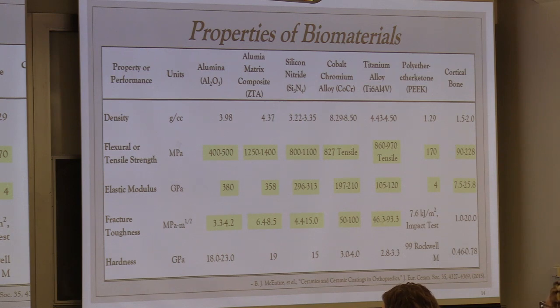But note that alumina has a fracture toughness which is essentially half or even a quarter of that of either ZTA or the silicon nitride material. And we're going to explore a little bit why that is the case. But these materials, the ZTAs and the silicon nitrides, are really the ones now that are a focus because of the fact that they can increase toughness a lot and they have very good strengths comparable to the metals that are out there. Well, of course, the metals fail by yielding, but ceramics fail actually by fracture.